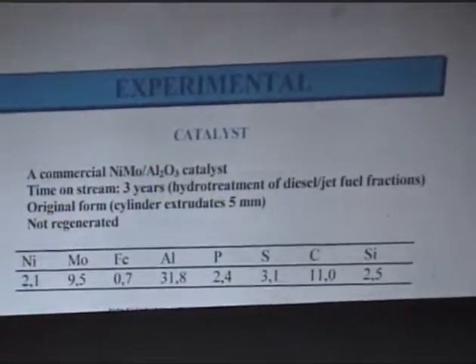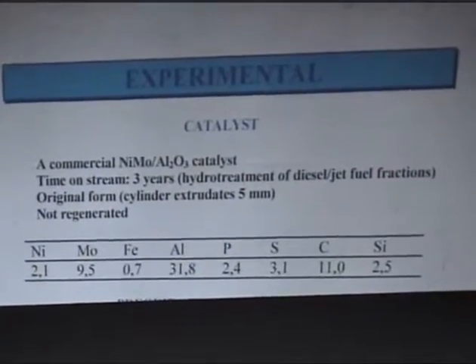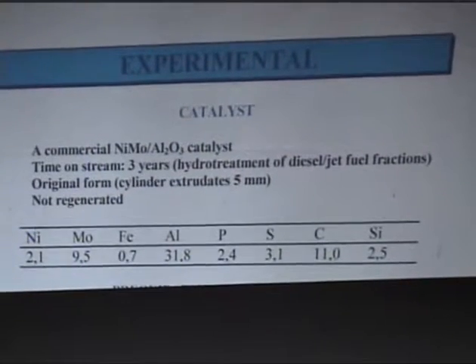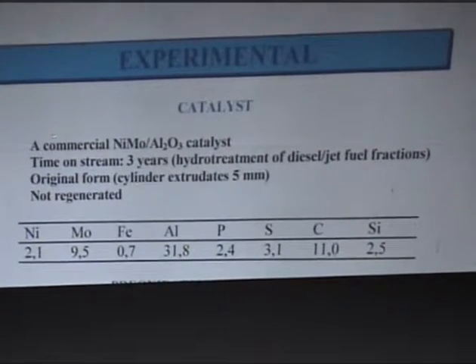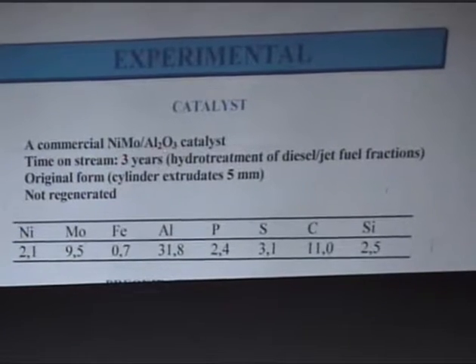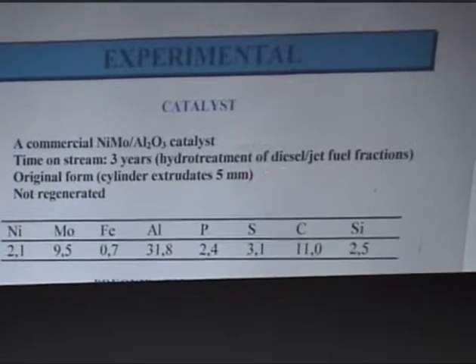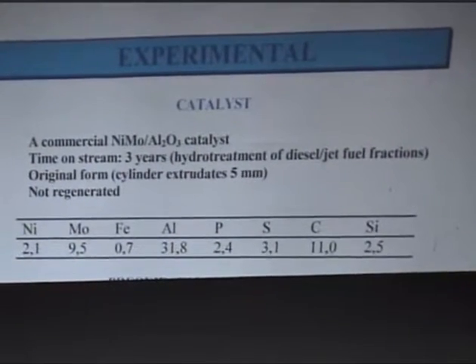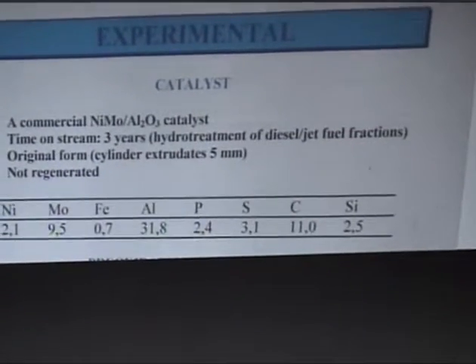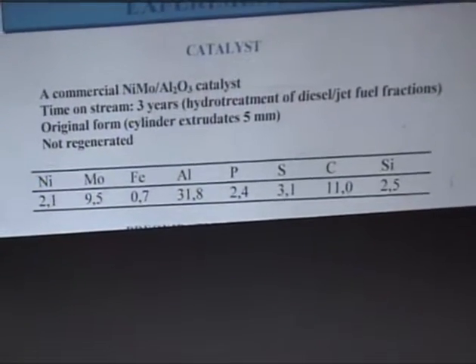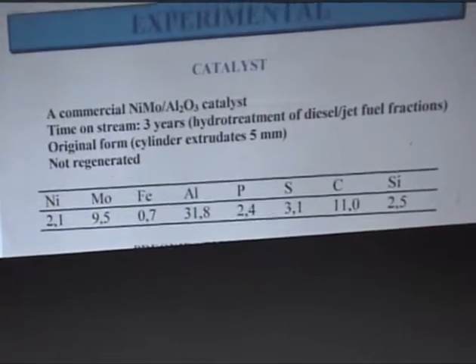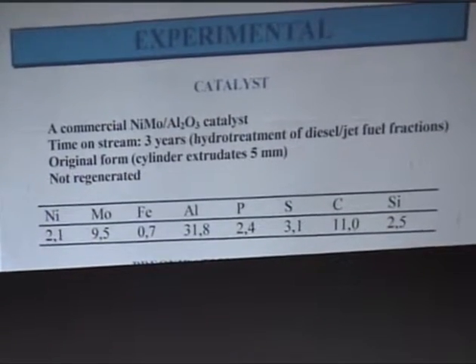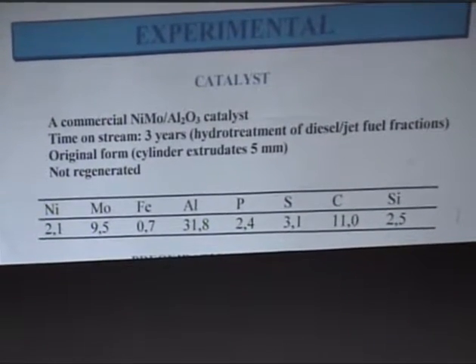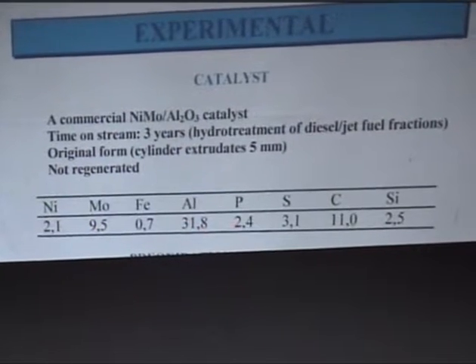The catalyst employed in our study was a traditional and common hydrotreating NiMo alumina catalyst, which was used for about 3 years for hydrotreatment of diesel and jet fuel in a Brazilian petroleum refinery. It was kept in its original form and it was not regenerated during its lifetime. As you can see from the elemental analysis, this catalyst contains two common additives, phosphorus and silicon.